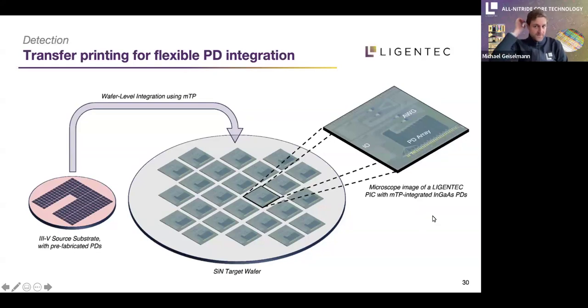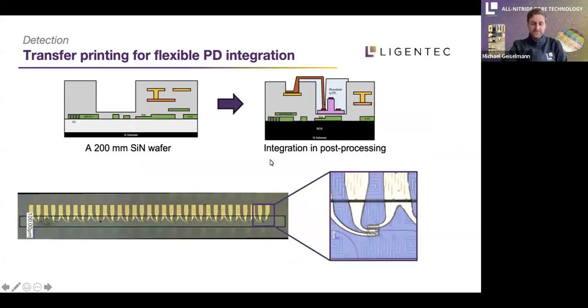In our first fabrication cycles, we did that with InGaAs photodetectors, where as described, we fabricated a 200 millimeter silicon nitride wafer, opened here the oxide window to get access to the evanescent field, and then placed the photodetector in that opening and did the contacts here. So here you see a fabricated device. The photodetectors are super tiny. This is the waveguide here that then evanescently couples the light to the photodetectors, and you have the contacts to do the readout of the photodetector.